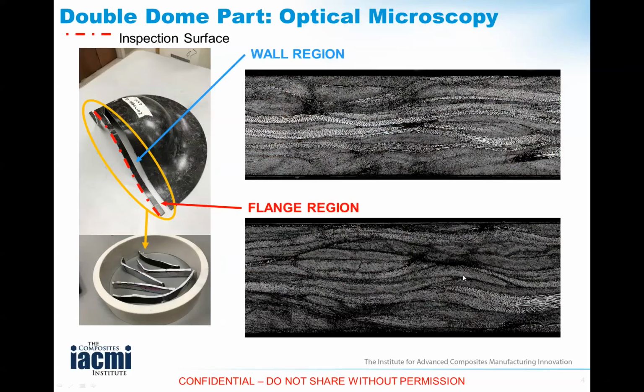Here is an example of optical microscopy of a series of sections that we are identifying here in red, location along a cut section, which obviously shows you the complexity of the platelets. The brighter and the darker regions on the right show you the fairly drastically different orientation of the fibers as these platelets are molded into the final component. So the key is, whatever database you generate for material cards needs to account for this transformation in microstructure.